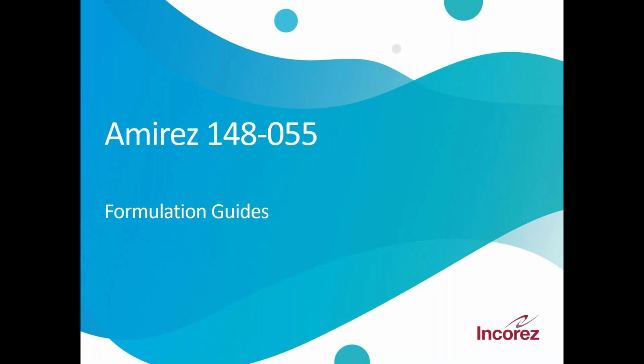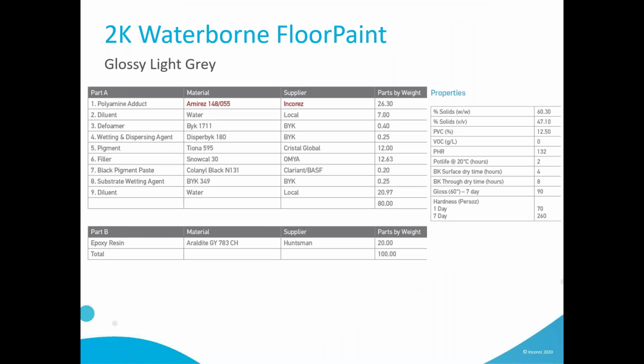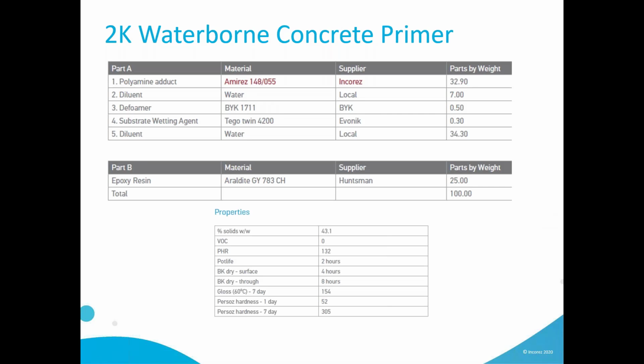I will now move to a few formulation guides that we've developed based on 14855. You can see here a light gray top coat formulated to be 0-VOC. You can see that the pot life is very good with 2 hours, but still quite fast drying time of 8 hours. Ultimate hardness being pretty high with 260 persoz with a good gloss. Similar performance is achieved for the concrete primer with this light formulation, still no VOC, fast drying, and very good gloss and hardness.